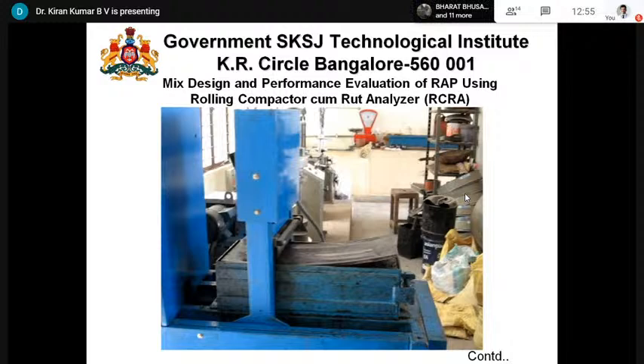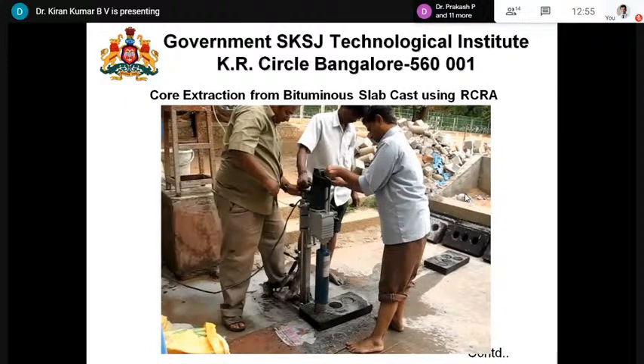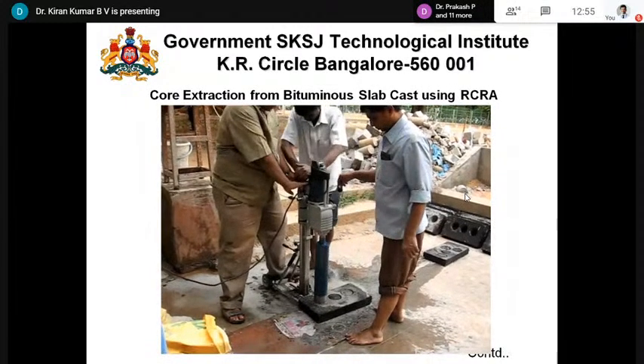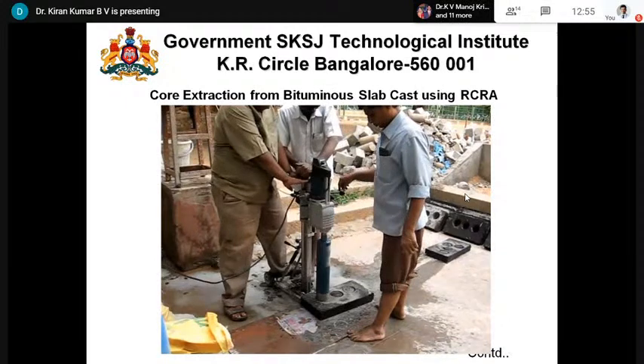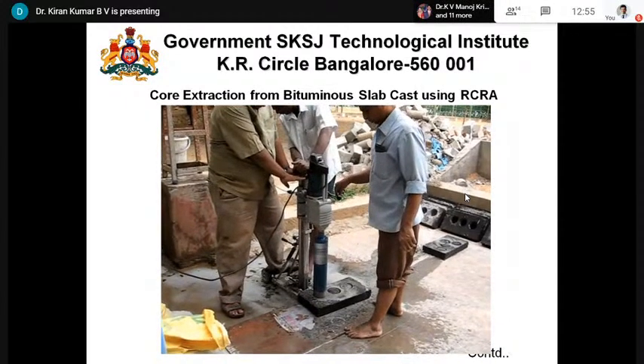We have fixed the binder content also for the new mix, which comprises 80% old recycled material, 20% new material, and a bitumen content of about 3 to 3.5%. You can see here, we have removed the cores. The cores can be taken out. We have used plastic, we have used CRMB and all.